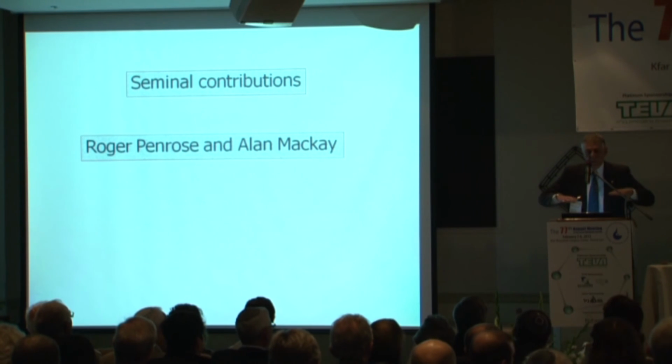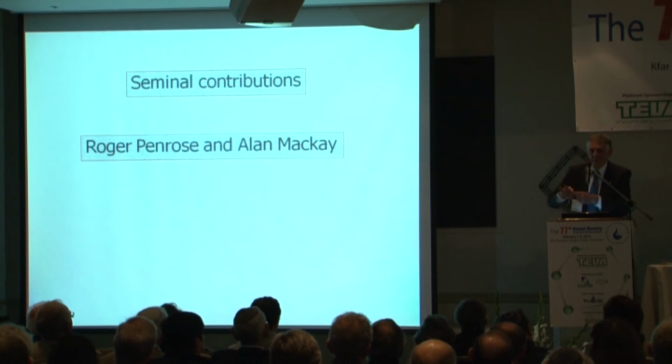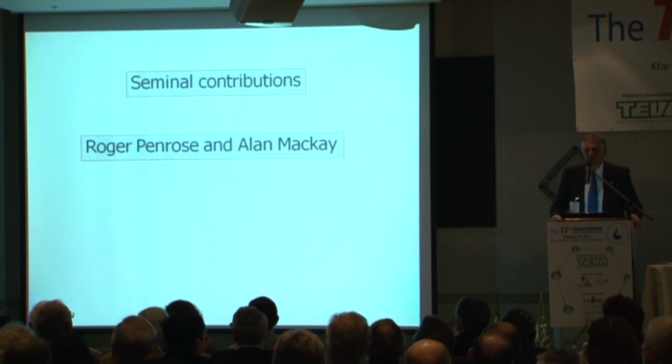The tiling was aperiodic. So this was the great discovery. What Alan Mackay did was to take Roger Penrose's drawings, shine a laser beam, and show by optical diffraction that they give a five-fold rotation symmetry diffraction pattern. And he published this paper in 1981.